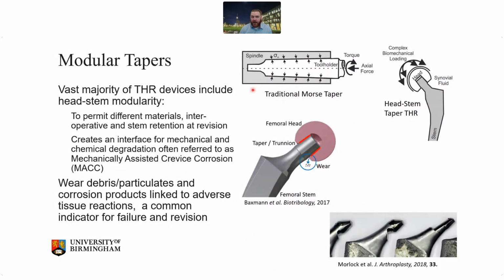They have a shallow matched cone angle. And they're also typically press fit on, and are used to transfer axial torque or force through the tool. It's completely different to how modular tapers are used in hip replacements, in that you typically have mismatched cone angles, shallow, short threads, and they're also subjected to complex biomechanical loading. So these things add another interface. They introduce a crevice corrosion interface and produce wear and degradation that way.